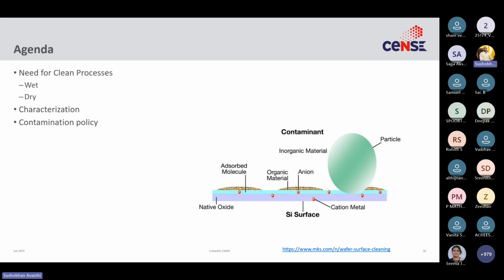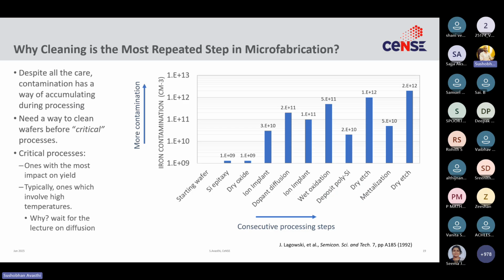Okay. This was the issue of contamination sort of stacking up that I was talking about. You start with a clean wafer and it has no detectable particles on it. You do your silicon epitaxy, and just because you did some deposition step on top, you would now detect some number of particles. Then you do some other deposition and you get some more particles, and then you go and do your ion implantation, which is a form of doping, and suddenly it jumps by an order of magnitude. And then you do some more processing and it jumps by another order of magnitude. All of this basically is to say that unless you figure out a way to arrest this, it will kill your device run very, very quickly.